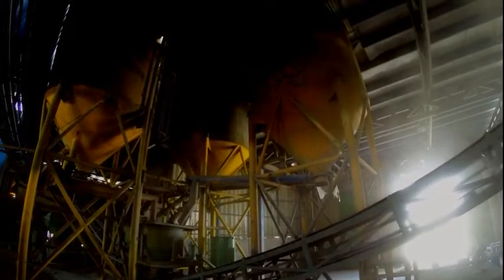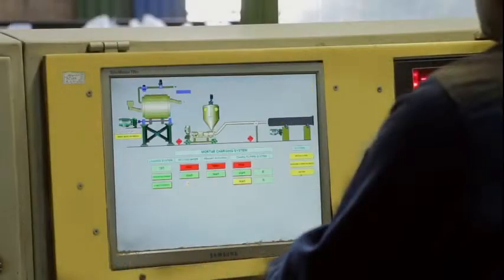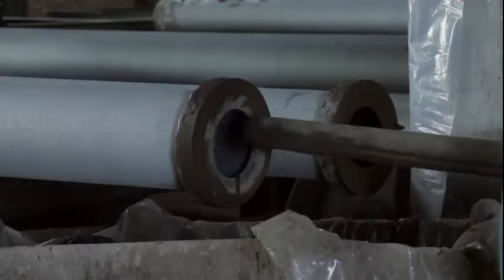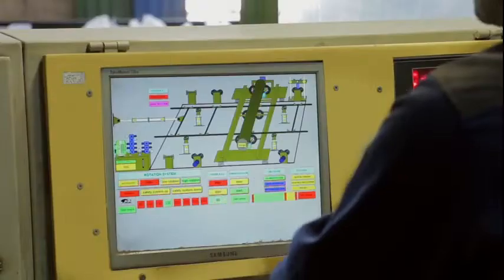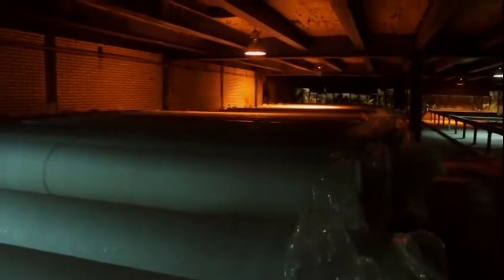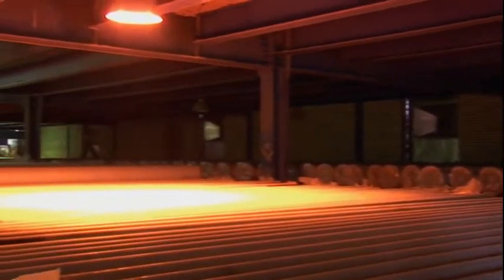The inner surface of the pipes are covered by a layer of cement with a minimum thickness of 2 millimeters by centrifugal method in order to transfer water hygienically and eliminate surface roughness coefficient, resulting in a laminar and smoother flow of fluid. The cemented pipes are placed in the curing section for at least 14 hours at a temperature of about 55 to 75 degrees Celsius to complete the cement bonding.